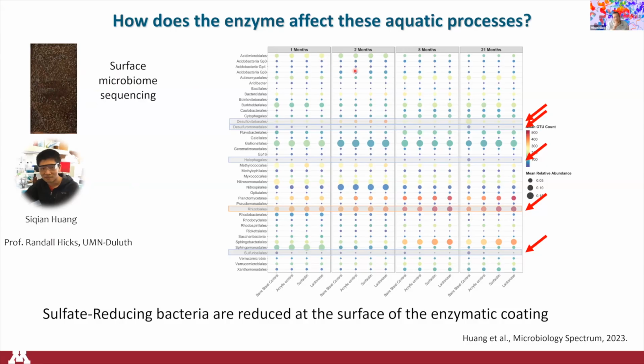And here you have a big and complex figure, and I'm not going to ask anybody to try to look into all of these little points here. But what you have is a representation of the microbial population on these different samples at 1 month, 2 months, 8 months, 21 months, as a function of treatment here at the bottom. So you have the different treatments. And we see very significant differences for all of these different taxa, highlighted by these arrows. And very interestingly, this was done on steel substrate. So in this case, these different taxa are what we call sulfate-reducing bacteria. This is a class of bacteria that reduce sulfate at the surface, in this case of those steel coupon material. And this class of bacteria are known to be associated with corrosion.